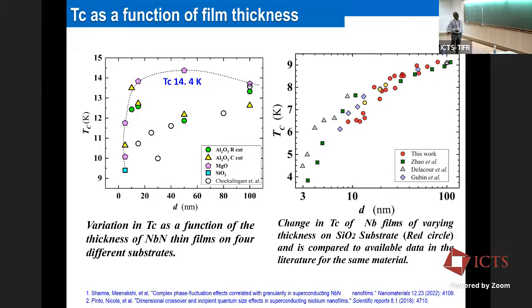So variation of TC as a function of thickness, if you can see, on MgO we are having a systematic variation in TC, like up to a film of 40 nanometer or 50 nanometer we are getting 14.4 Kelvin. This is with the thickness you are having on silicon. So in this case, we are comparing, this work has been done by Professor Nicola Pinto, and he published it. And this is the work in our collaboration, basically. So you can see that on MgO we are having systematic behavior, otherwise some scattering is there.